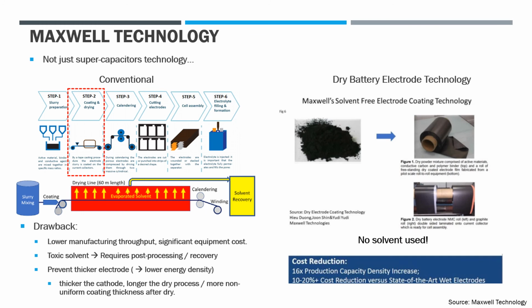So to resolve these problems, Maxwell came up with solvent-free technology, which they call dry battery electrode, where they don't use the solvents, but use direct coatings onto the base material, such that all the problems I mentioned earlier would be significantly resolved, and that production capacity would increase, the cost would be reduced, and potentially you could increase the energy density by having a thicker electrode.